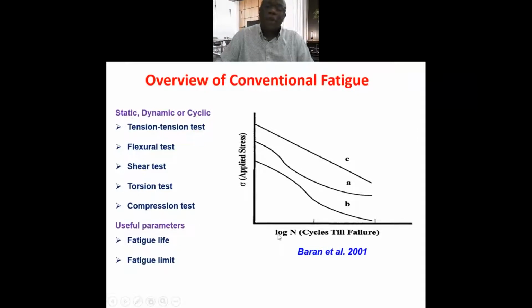Fatigue testing can be done using tension test, flexural test, shear test, torsion test, or compression test. What we get from fatigue is known as the SN curve, the stress versus number of cycles plot. You can see three characteristics here. We perform fatigue tests to determine the useful parameters, which are fatigue life and fatigue limit. Fatigue life is the maximum number of stress cycles that the material can absorb before it fails, while the fatigue limit tells us the stress level below which fatigue failure will not occur.